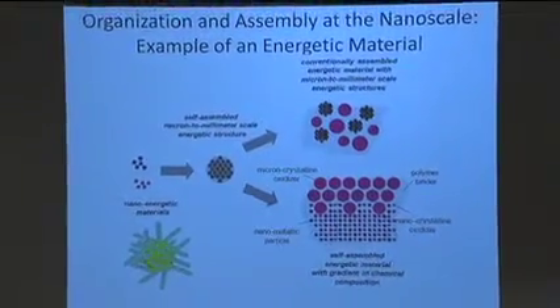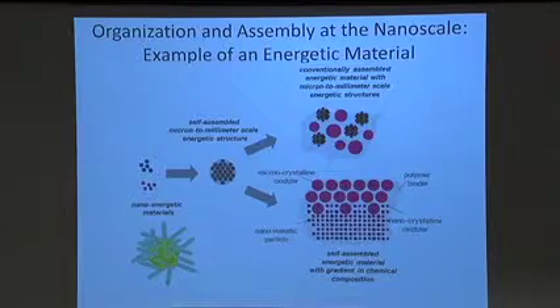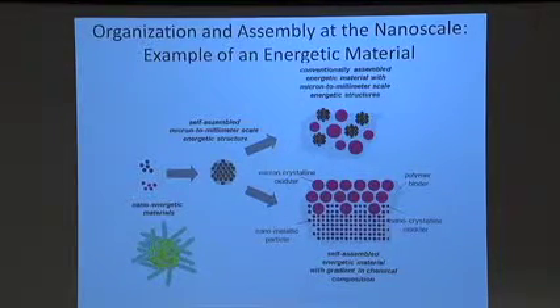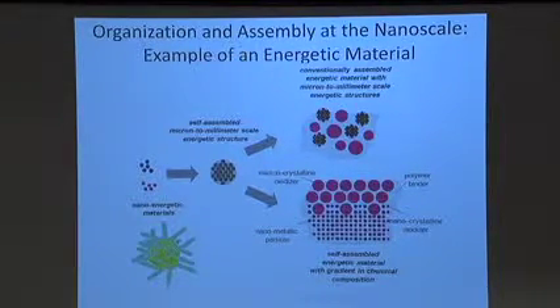And if, for example, I were to somehow ignite the top surface here, and this material would start burning downward, because of the larger length scales I'd have a slower burning rate in the beginning. And as the material burns down and I transition to this region here, I would accelerate the rate and burn much faster. But I would know how that would happen a priori through the design process.